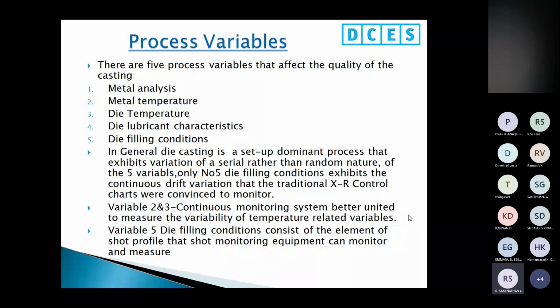Die filling condition exhibits continuous drift variation that the traditional XR control charts were designed to monitor, so they can be used for the die filling conditions. Variables 2 and 3, metal temperature and die temperature, are better suited to a continuous monitoring system to measure the variability of the temperature related variables. That means some type of thermocouples can be attached to the tooling, sometimes in the material, to monitor the 2 variables. Variable 5, die filling condition, consists of elements of the shot profile that shot monitoring equipment can monitor and measure. For example, the slow speed, first phase speed, second phase speed, second phase starting point, and intensification starting point can all be monitored through the machine monitor.